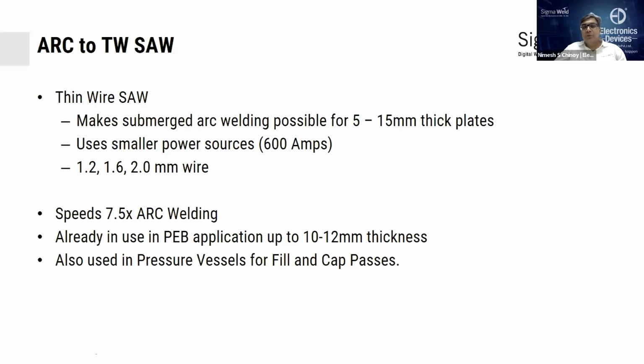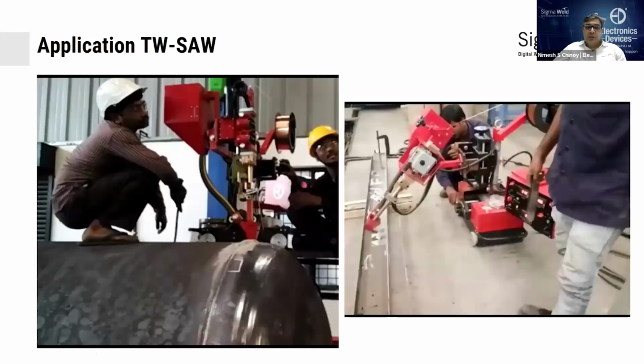Already it's a standard usage in PEB application up to 10 to 12 mm thickness, and also for pressure vessels for fill and cap passes. So here's an example where a 5 or a 6 mm thick vessel is being fabricated using thin wire SAW. This is a 1.2 mm wire, and the productivity is going up 7.5 times. Not to mention, when you use the submerged arc process, the weld quality also improves, deposit also improves.